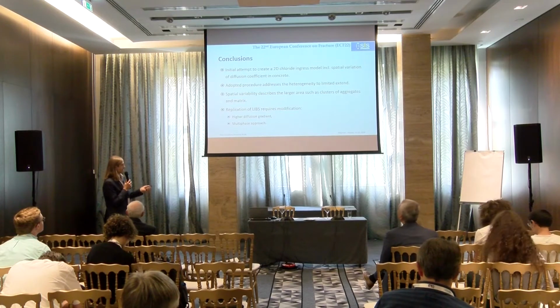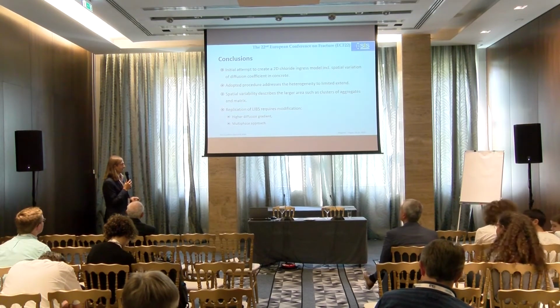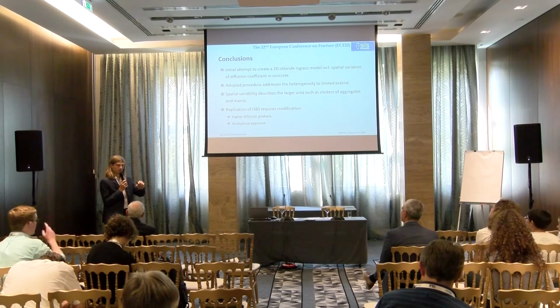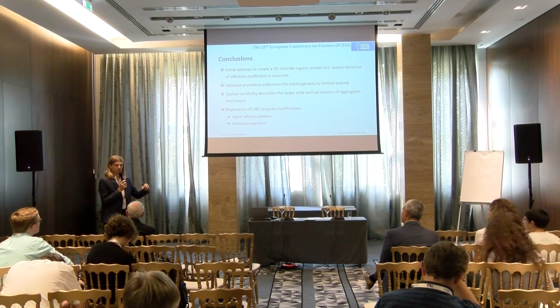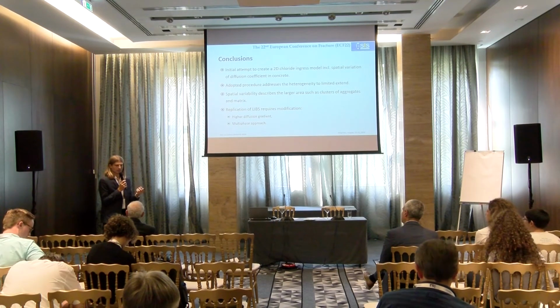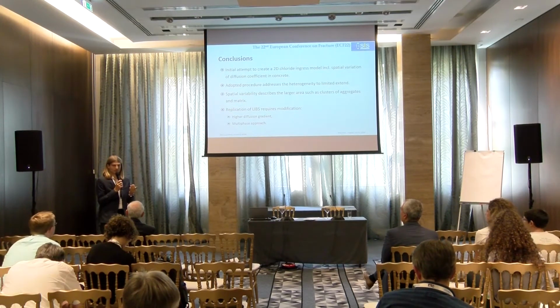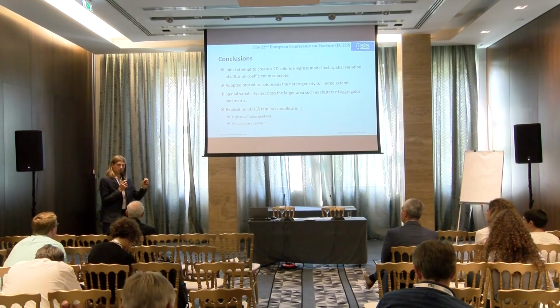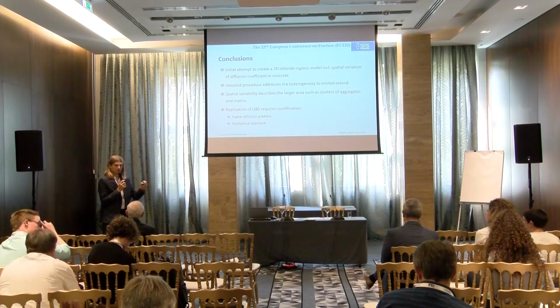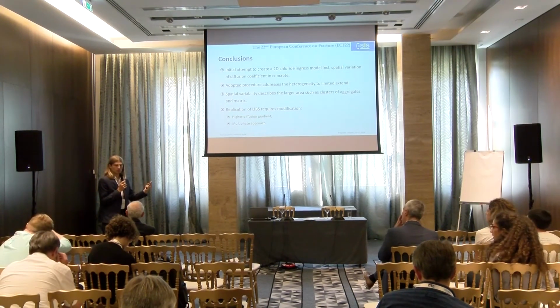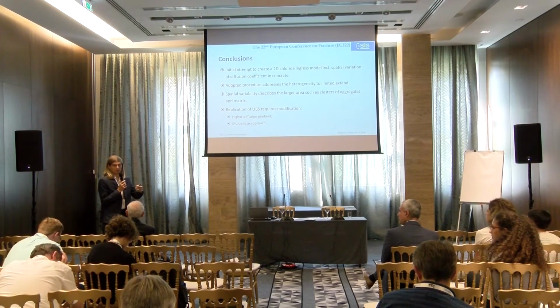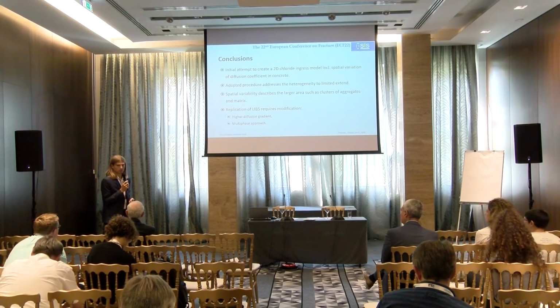And it is given here. First is the possibility to put a higher diffusion gradient into the spatial variation, or to use the multi-phase approach. It means that, for example, the aggregate will have zero ability for the penetration of chlorides, and we will concentrate only on paste. And then within that paste, we can use the spatial variation and neglect basically the aggregate. This is a possible way how to continue.